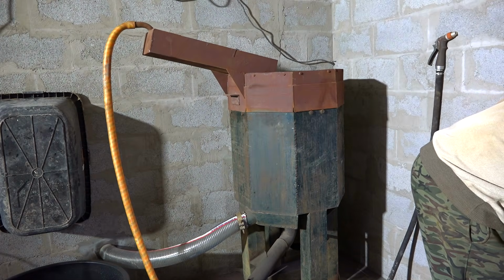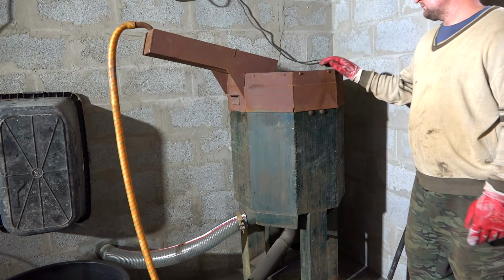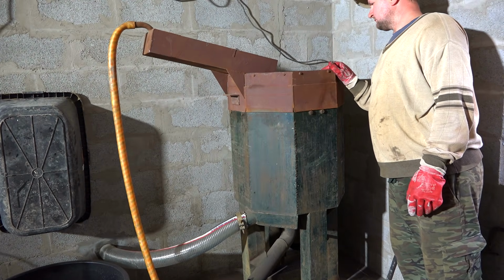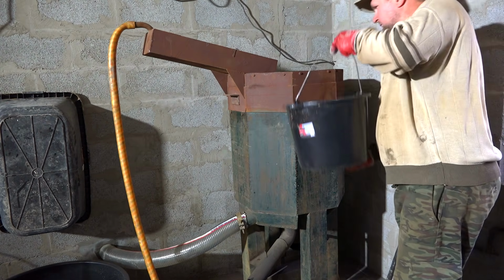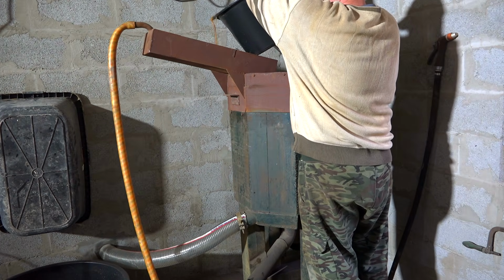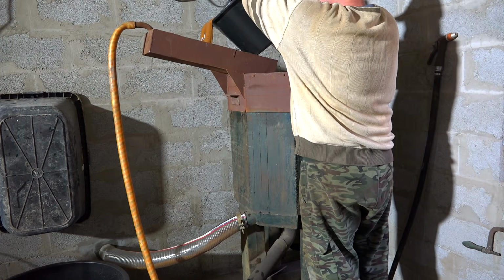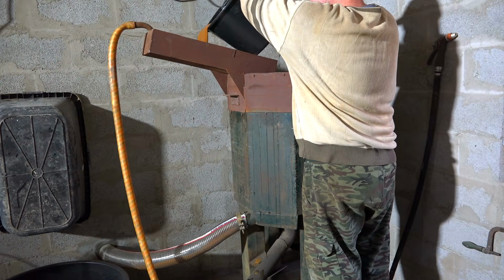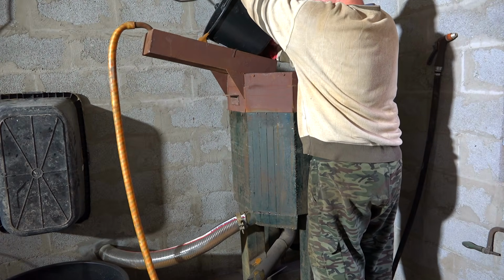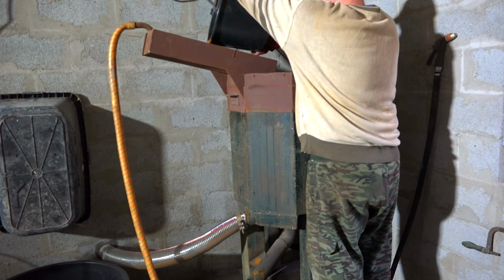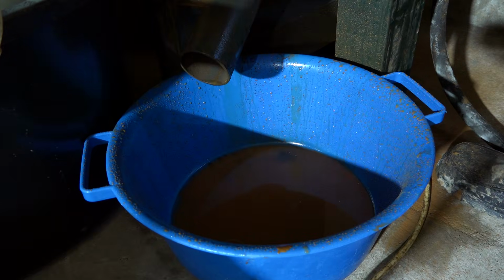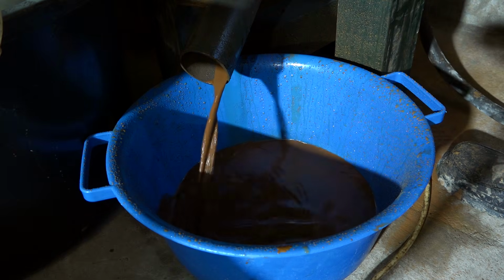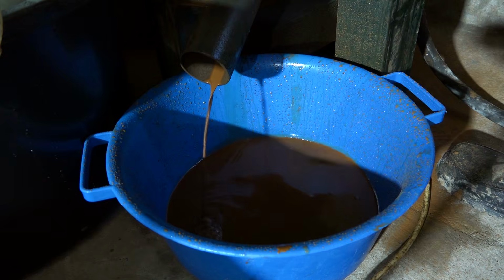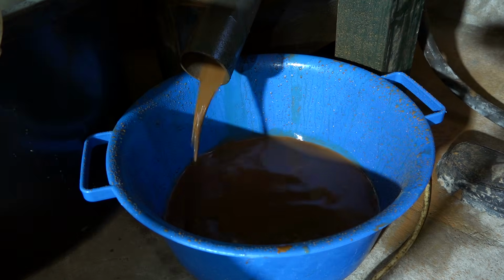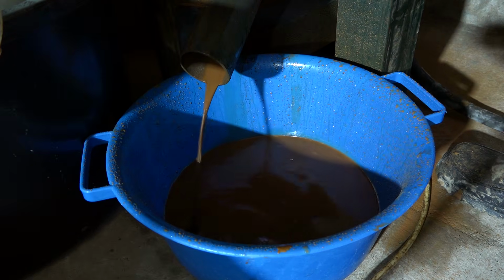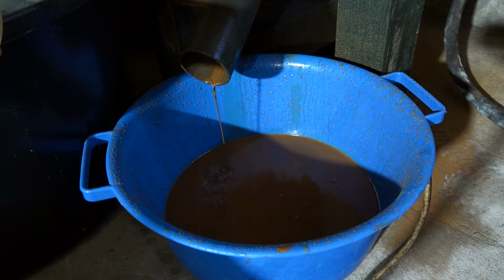Centrifugal enrichment is one of the best ways to concentrate precious metals. But for it to work, many device parameters must be considered, otherwise, the results may not be optimal. 15 minutes passed, I rinsed half the volume, turned off the miracle device, and now I have the concentrate you see. It contains varying amounts of gold, 15% visible and 70 to 85% dust, the difference depends solely on the ore.